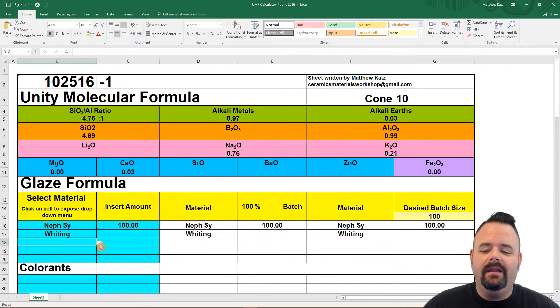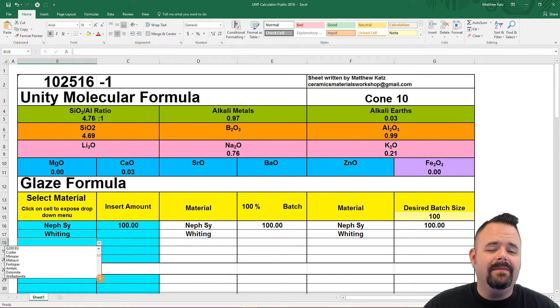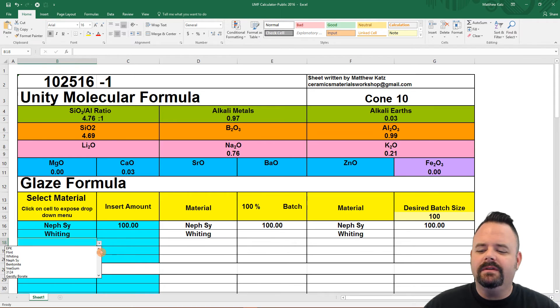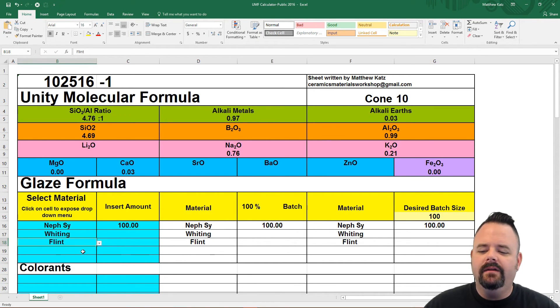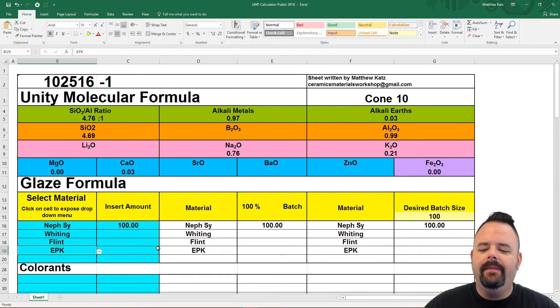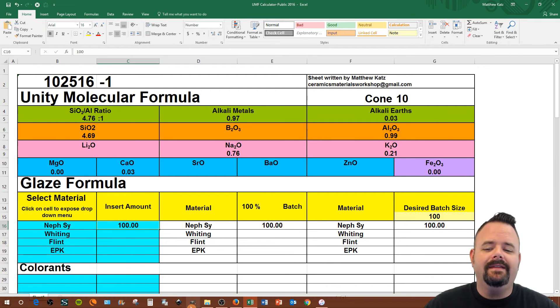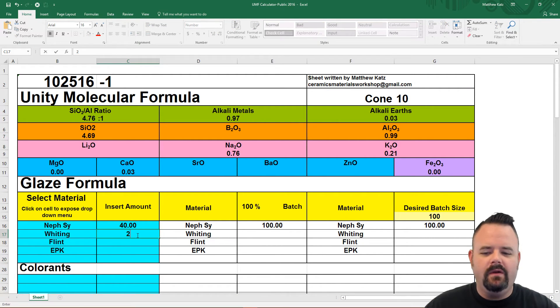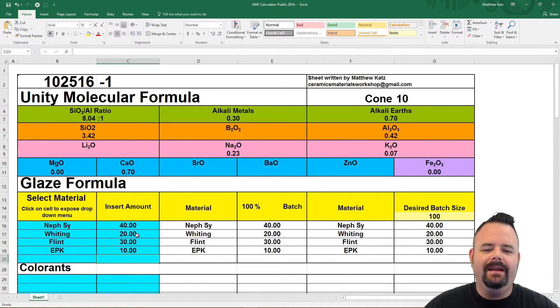The listing is a little bit random but if you click on the box and sort through them, pretty much everything is there. If there's something missing that's not that common, I tend to keep this to American materials — let me know on the discussion forums at CeramicMaterialsWorkshop.com. So we've got this whole list of materials and we're just going to run a simple recipe of nepheline syenite, whiting, flint, and EPK. We're going to program in our standard 40-20-30-10, so 40% nepheline syenite, 20% whiting, 30% flint, and 10% EPK.